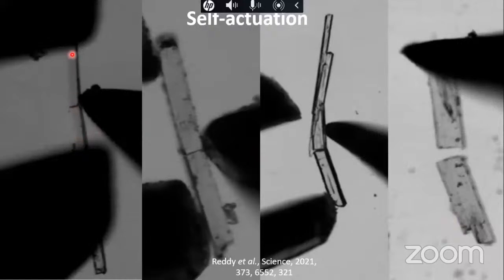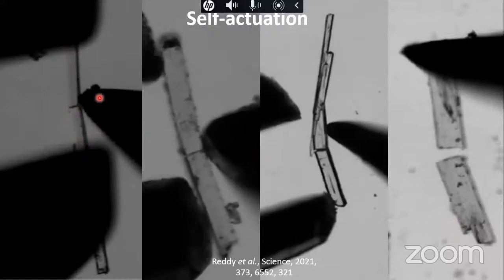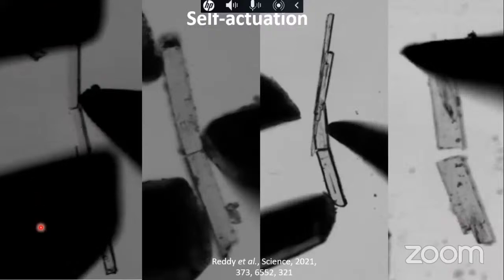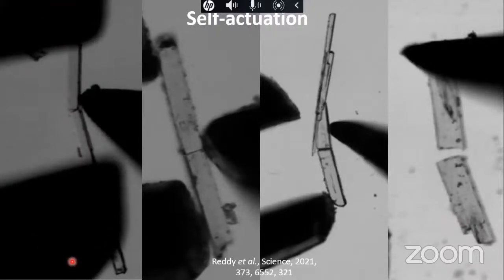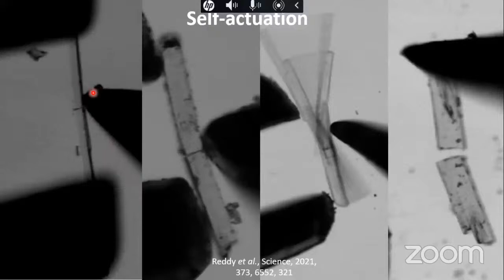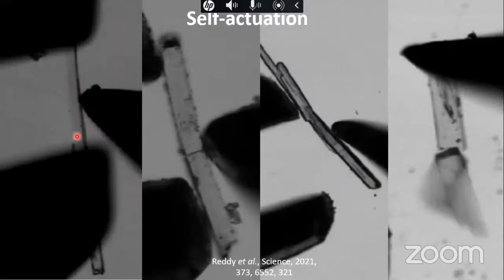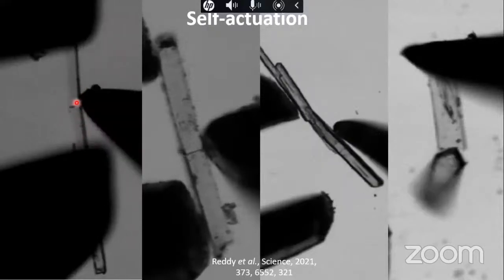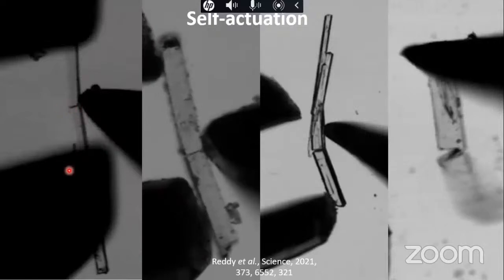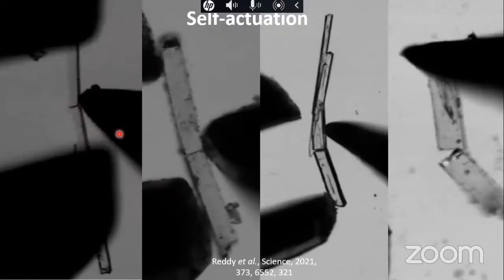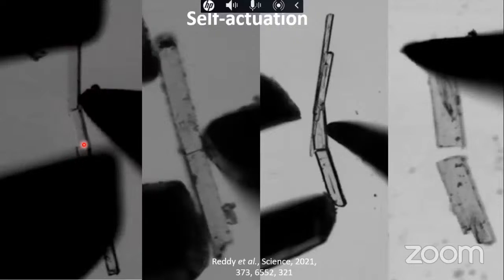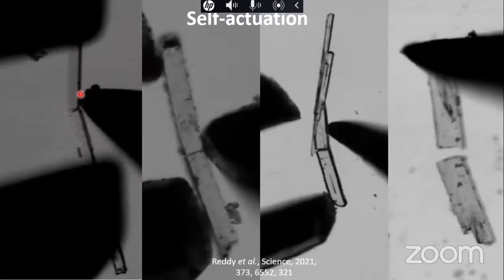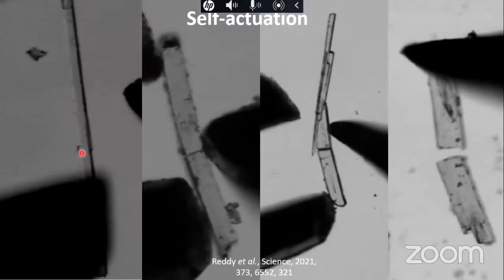And as you can see here, this is a long crystal, and this is a needle, and you hold it from one side with the forceps. These are metal pins, and you're pushing it using a needle. So you develop a big crack, and as you can see, this is a crack. And when you leave it, the crystal comes back and it's sewn, right? As you can see here, there's a big crack and a big gap.